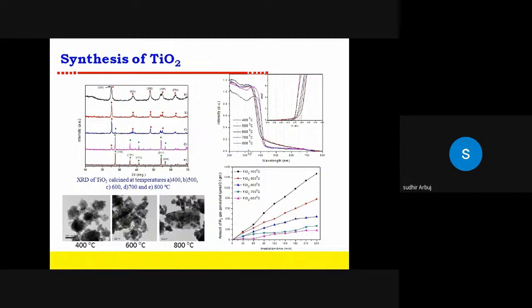The TiO2 prepared at 400 degrees centigrade is showing a broad XRD peak. A broad XRD peak indicates the formation of nanosize. With heating, the size is increasing, and at 600 degrees centigrade, the peak at 2 theta 27 starts appearing. At 700, the peak at 27 is higher and the peak at 25 is lower. And at 800 degrees centigrade, the peak at 27 degrees is higher.